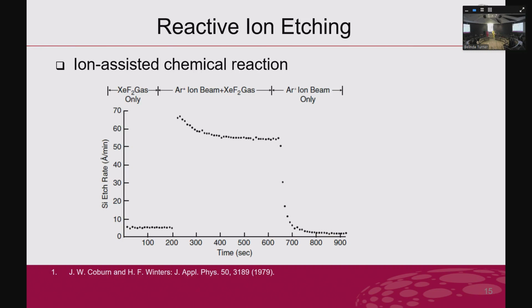And here the next slide is, because I said during the RIE process it combines chemical and physical. So here, if you only have the fluoride gas on the left side, actually the etch rate is quite low. Then if you only have argon ions to bombard your surface, it's more physical, and the etching rate is also low. Only when you mix the two processes at the same time can you come up with a higher etch rate. So if I just use a physical process, the efficiency is quite low, and chemical alone is also very low. You need to rely on both working at the same time.